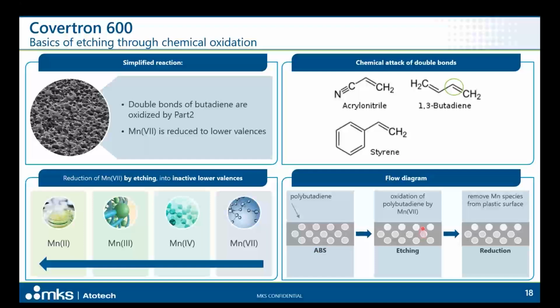In the flow diagram that we showed on the screen, you can see as a summary the etching step. So we have the polybutadiene in ABS. We create the etching pattern by the oxidation of this polybutadiene by manganese 7, and finally we have a reduction step that will remove any manganese species that could remain on the plastic surface.